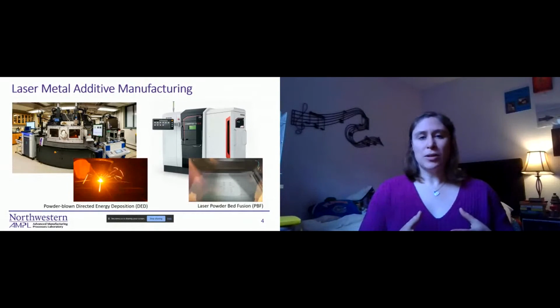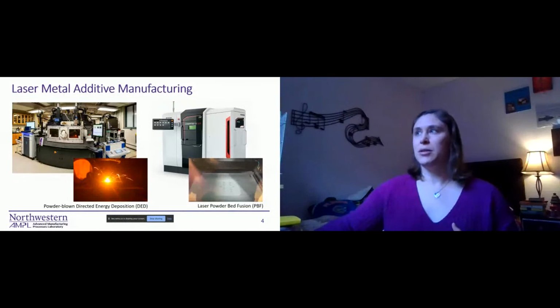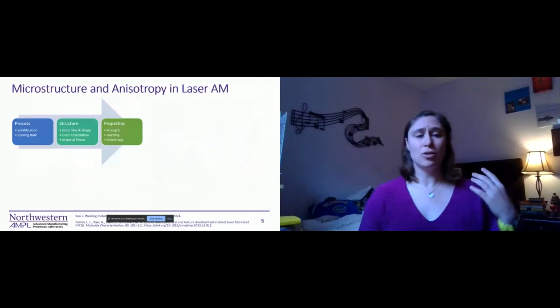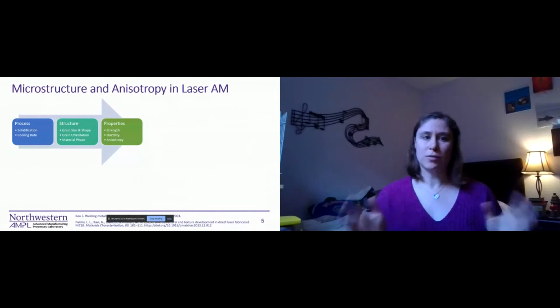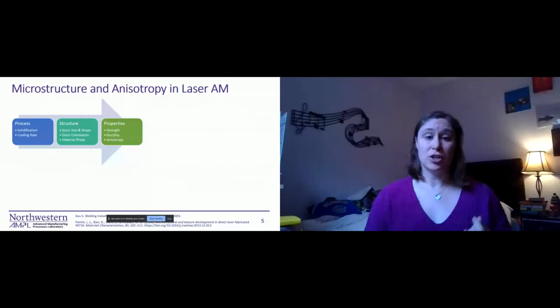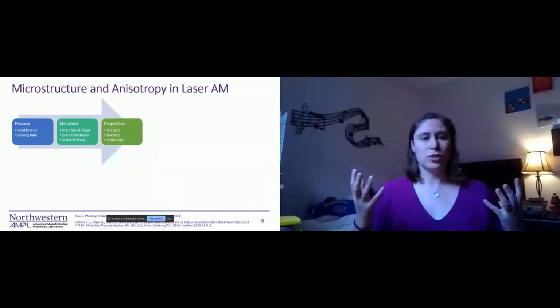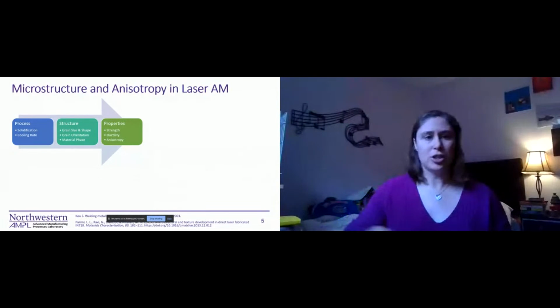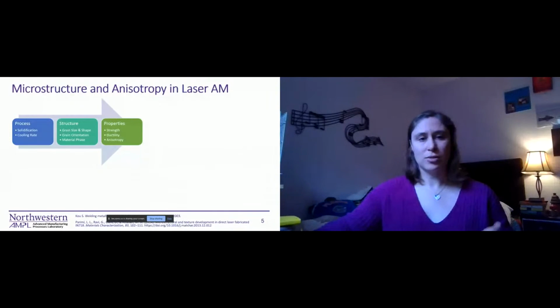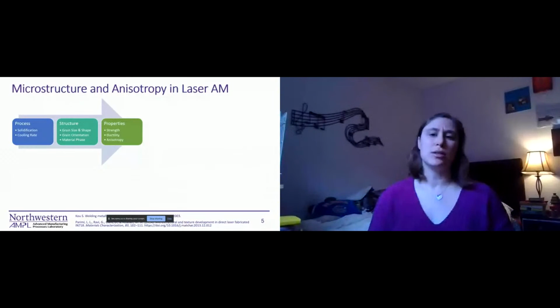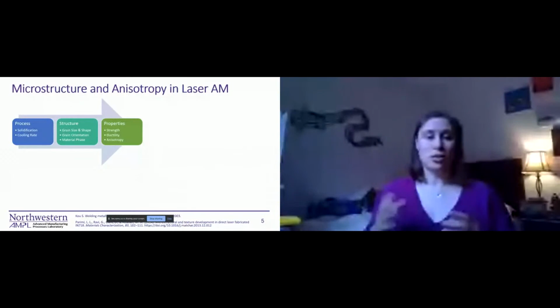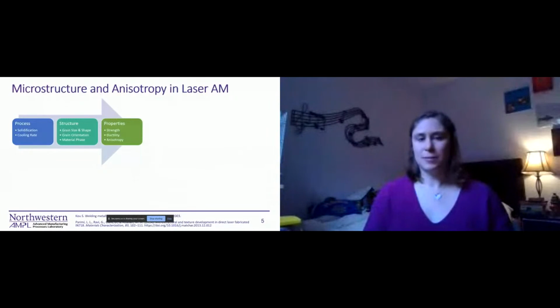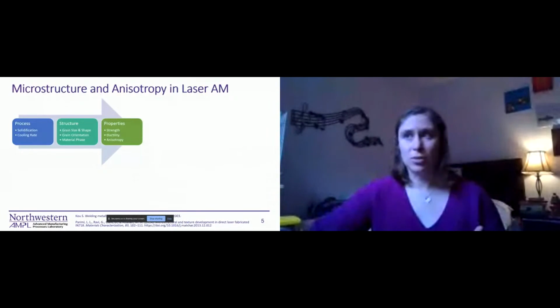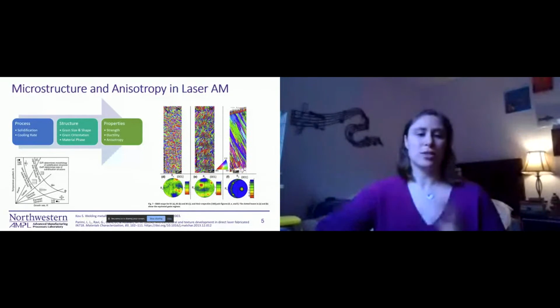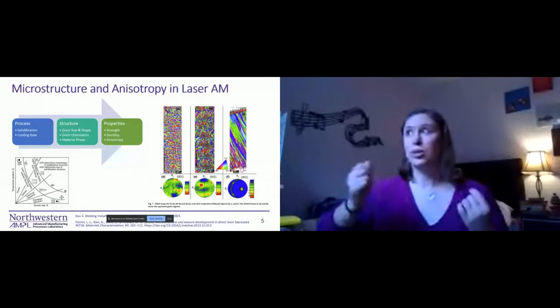So laser metal additive has very unique structures in as-built materials. Looking at the process structure property relationships of these materials, we have very fast solidification and cooling rates. This obviously controls the structure of our material, the grain shape and size. And a lot of the time, the fast rates and the thermal gradient throughout the material actually lead to very elongated and columnar grains, as you can see on the right. So this could be desirable in some cases, but it's important to understand the structure of your material and how you can change it.